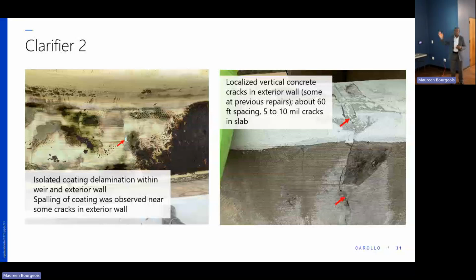So again, same thing, recommendation, visual assessment every 3 to 5 years, lab testing every 10 years with the non-destructive testing, and then the repairs and the coating system protects the cover of the concrete in the long run. And that work we recommend to take place in the next 3 to 5 years.